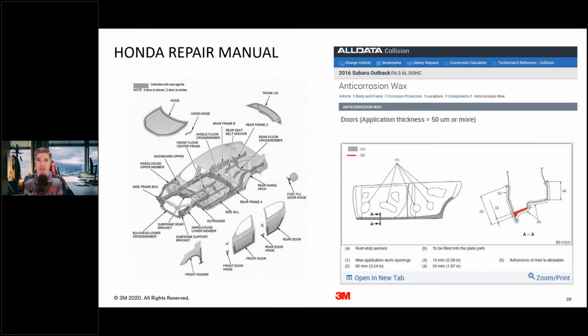And that foaming action does go away, but it allows that to stick to the sidewalls. It doesn't drain and run out, right? There's a minimal amount that does flow as that foaming goes down and gets into like the lower cavities in these areas and runs to these low spots to protect it. But more importantly, it sticks where we want it. So especially like in sail panels and getting coverage up on top, it's very important to point that out.